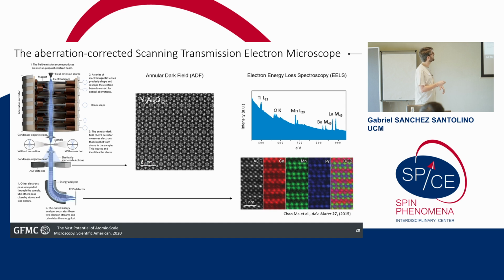And this is all thanks to this part of the microscope here, which is the aberration corrector. In the microscope, we are using magnetic lenses, and usually we have spherical symmetry magnetic lenses, but these have some aberrations, right? So we use this aberration corrector, which is a set of magnetic lenses with different symmetries. We have quadrupoles, hexapoles, octupoles, etc., to fix the shape of the probe and correct the aberrations.